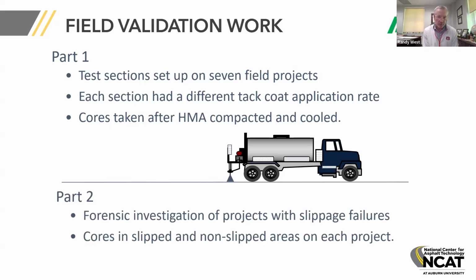Part 2 of the field validation work was going out to field projects around Alabama where there were slippage failures. And we took cores both in the area where there was slippage occurring and on the same project away from that slippage area so that we could have a bond strength comparison of the good and bad areas.